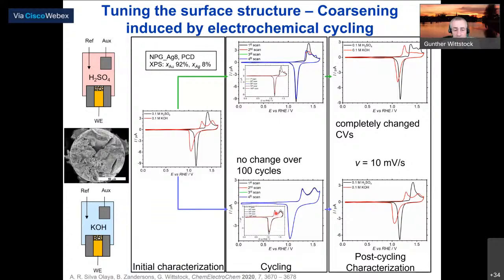However, if we do the same thing in an alkaline solution, the shape of the voltammogram stays the same for over 100 cycles. There are only minor changes. However, if we then transfer this sample, which was cycled 100 times, to sulfuric acid, then we immediately get the same response as we had here.